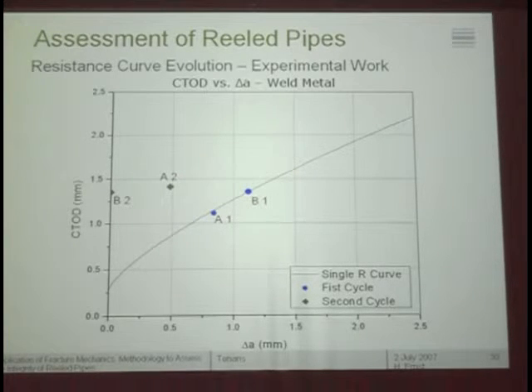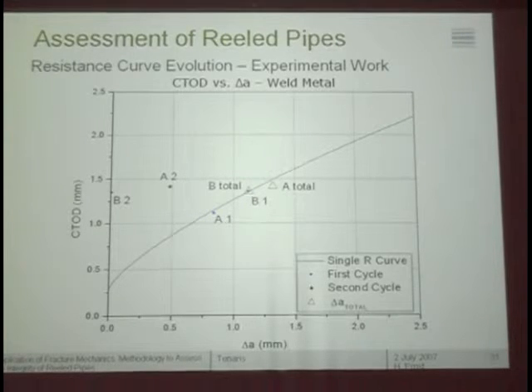How can you put a rule that says how much extension you will have in the second cycle? So as I said, if you add together the two, that is at the maximum CTOD, you add how much you got for this one and how much you get for this one, so you will move this point towards the right, and the same thing here, B1 and B2, you add the two crack extension levels for both and put it at the level of the second CTOD.